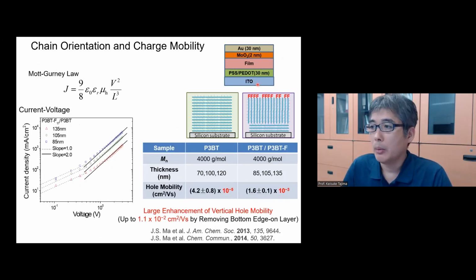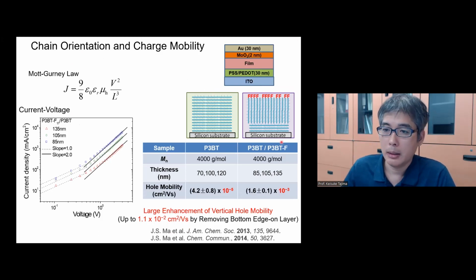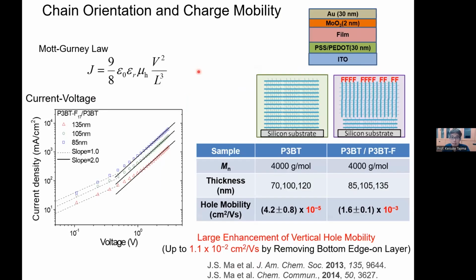Another thing is, of course, the charge mobility. As I said in the introduction, we can expect large mobility in the vertical direction. We measured this hole mobility by space-charge-limited current measurement with multiple film thicknesses. And what we found is that, compared to these two situations, we got a much higher hole mobility in the vertical direction than with this ordinary edge-on orientation. So a large enhancement can be observed.